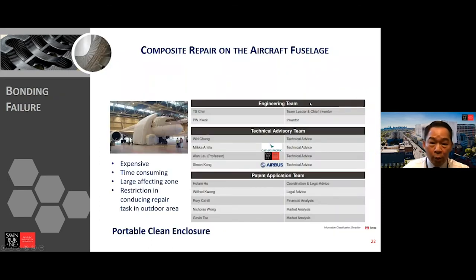As I mentioned already, for composite repair we need to control the environmental conditions. So now there is something like a portable clean enclosure structure. They put the whole thing in place over the area that you want to repair, and then control the pressure, humidity, and dustiness. But the problem is that not all runways or repair sites have a platform or floor flat enough to allow you to put the whole machine, the hot and cold chamber, on the side of the aircraft.